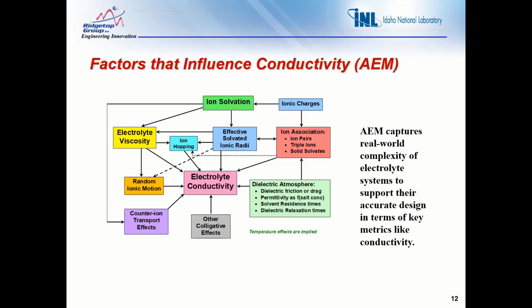So within this particular focus, we see that electrolyte conductivity is impacted by viscosity, which is kind of an obvious thing if you look at the Stokes equation for ionic conductivity. But there are several things that influence viscosity in and of itself, such as ion solvation, the sizes of the ions, and other factors that fall behind viscosity. So going around looking at some of these contributions, there are probably 6 or 7 that are quantified within the model as it runs, and there's a special report dedicated to these different factors that contribute to conductivity.